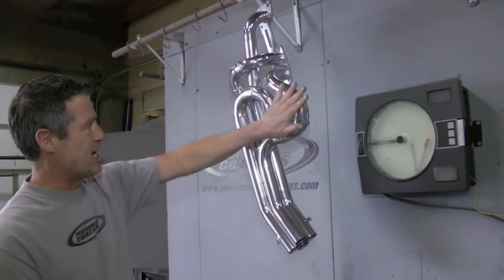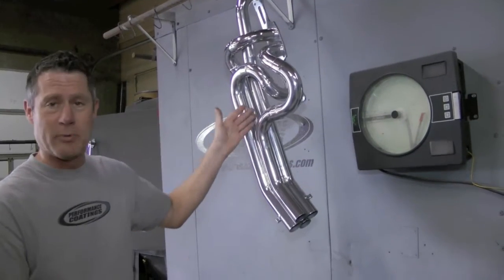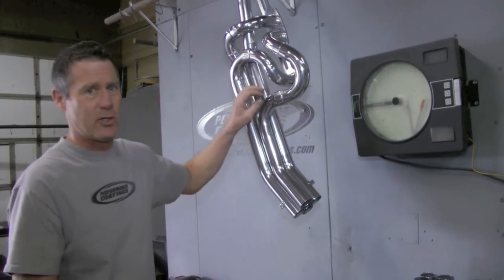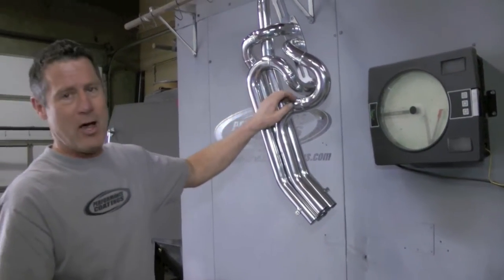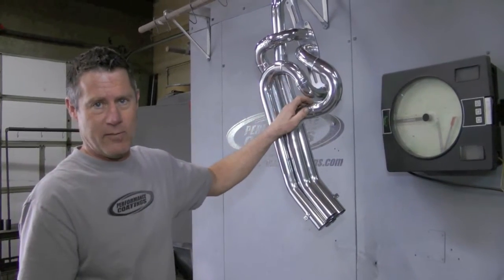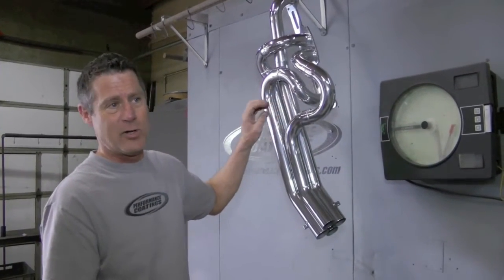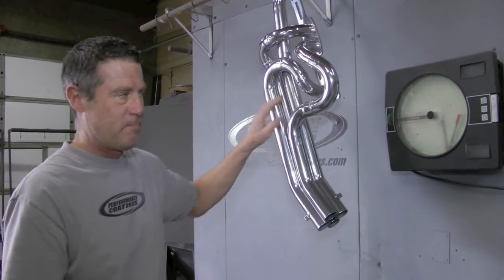Ceramic coating reduces radiant heat. This is good up to 1300 degrees here, and the limiting factor is the fact that it has aluminum powder in it. Aluminum oxidizes at 1350 degrees, so you can't exceed that or you change the structure of the aluminum.